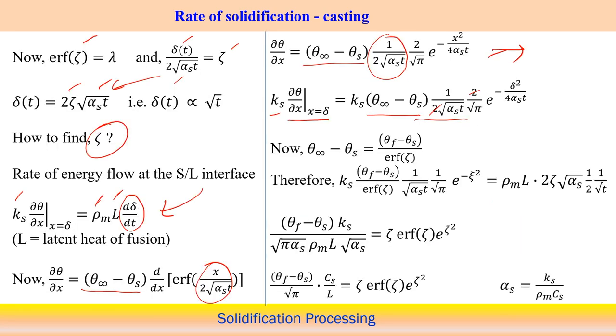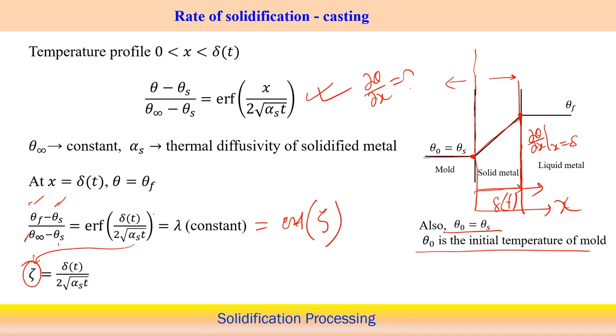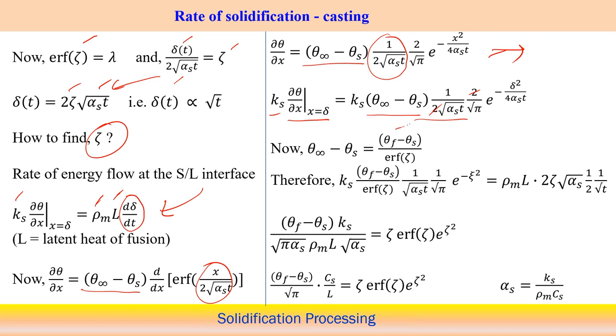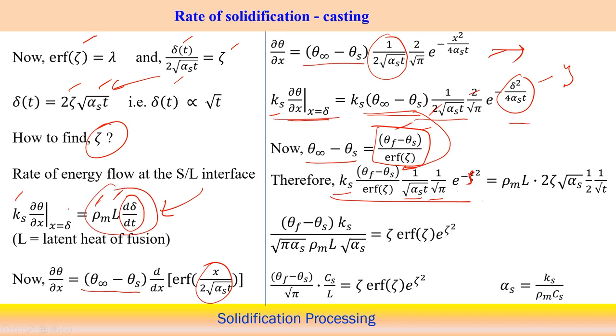Now, you see that we are calculating theta infinity minus theta s in terms of the error function zeta and theta f minus theta s, so we get theta f minus theta s by the error function zeta. Now, k s into del theta, we put this value of theta infinity minus theta s here, and then we get theta f minus theta s by the error function zeta, 1 by root over alpha s into t, 1 by root pi into e to the power minus zeta square. This should be equal to, from the energy balance, the heat flow rate, rho m l into d delta by dt.